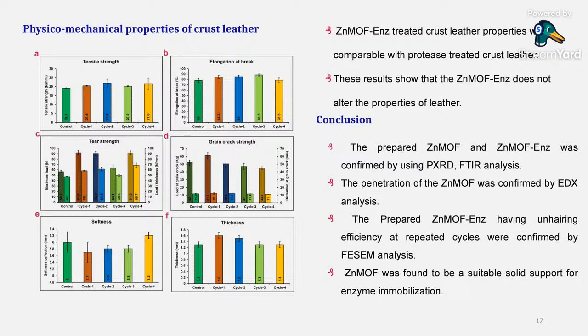So we looked at softness, thickness, grain crack strength, tear strength, tensile strength, and elongation at break. In all the cycles, up to 4 cycles, it is giving very good, nice results. So this is the conclusion. We prepared the ZnMOF with the enzyme immobilized, because this is not just an adsorption process, as an adsorption process would lead to leaching of the enzyme.